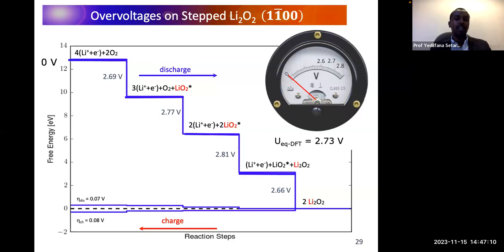Computationally, we got 2.73. If you remember, in the experiment we found 2.9 volt. So the experiment and the computation are in good agreement. From the four steps, the last step, the last addition of lithium, is found to be the limiting discharge potential, because this is the smallest energy that I got from these steps. And the third step is found to be the limiting charge potential. This is the highest one.